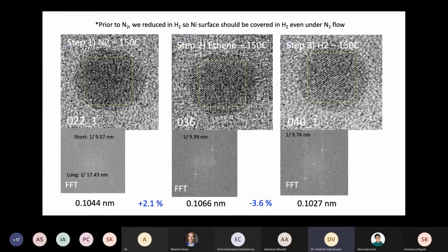So again, we took our catalysts to the reaction temperature that was interesting. For the ethene experiments, that was 150 degrees. For the carbon dioxide experiments, which we also did, that was 400 degrees. In the beginning, we just purged with nitrogen, and we flowed the reactant. And after we flowed the reactant, we flowed hydrogen. Every single time that we did this, every single nanoparticle that we checked, we always saw an expansion of our facet. We did a fast Fourier transform. We always saw that these lattice fringes expanded by about 2%. And once they contracted, there was a bit of a bigger standard deviation across the different nanoparticles that we measured, but it was about 2 to 4% contraction again after we flowed hydrogen.